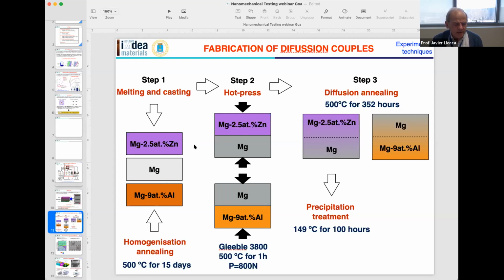Then the second step is you cut these two parts and you create the diffusion couple of magnesium 9 aluminum and magnesium 9 zinc. And then you do a little bit of hot pressing in a Gleeble system. You do that to create dislocations and plastic deformation in this region. And these dislocations are going to nucleate many different grains, because you want to have grains with different orientation.